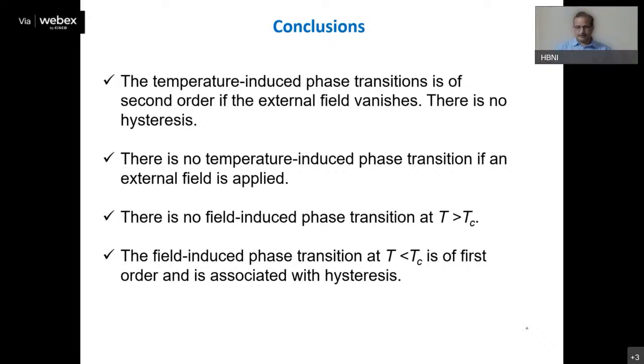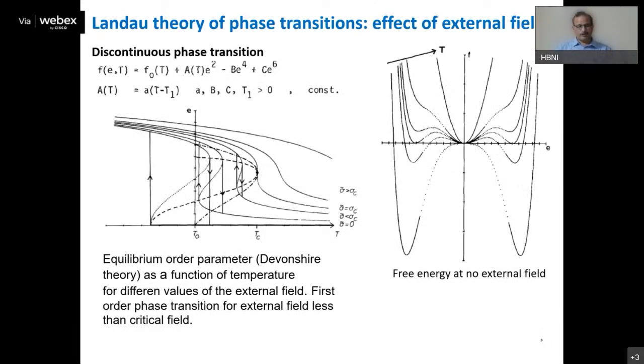Now let us take the second case. When we are considering the first order phase transitions using the Devonshire theory, here we have included one more term. So in case there is no field, we have this kind of free energy curves where the kink appears at some value where the order parameter has non-zero value and this phase becomes the stable phase. We have a discontinuous change in the value of order parameter.